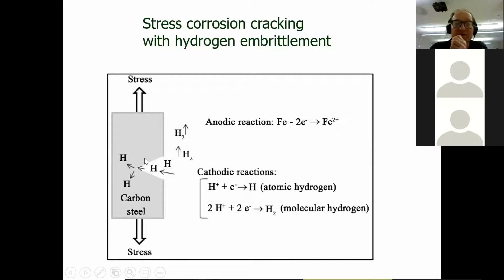And it diffuses all inside the metal surface. It goes everywhere inside the metal. And in particular, it goes down the grain boundaries. And this causes the metal to change its physical properties in such a way that it loses its ductility and it no longer can be bent. Instead, it becomes brittle. And any material that's brittle, that's under stress, will crack and fail.